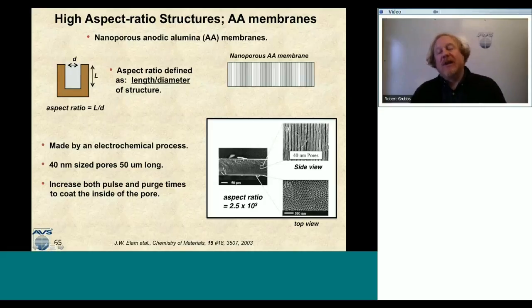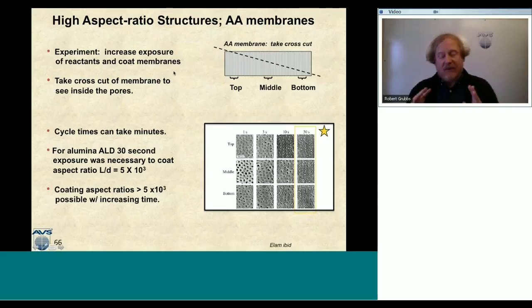But what we need to do is accommodate the molecular flow of the ALD precursors going down the trench and then the ALD byproduct coming out of the trench, in order for a successful conformal deposition in these anodic alumina pores. So that's exactly what was done. The idea was that we were going to deposit alumina at different exposure times, different pulsing times, and purge times, on different membranes. And we're going to cut the membrane from corner to corner. And we're going to analyze how much film was deposited at the top versus how much film was deposited in the middle. If the middle is thinner than the top, then we know we haven't waited enough exposure time to get the chemicals to go down that.